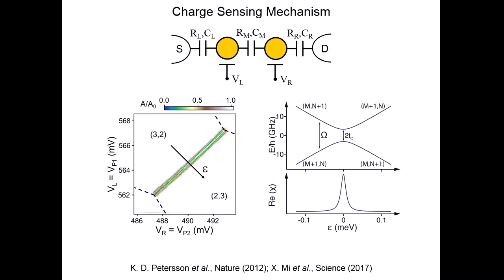Can you have an intuitive picture of what's going on? So here's what I'd like you to imagine. You have your left and right dot energy levels, and the typical energy scale associated with a quantum dot is the charging energy, which is millivolts. The typical photon energy at about 8 gigahertz is about 30 microelectron volts, much, much smaller than a charging energy. So if the energy levels are detuned like this or like this, there's no interaction between the light and the electron because they're too far out of resonance.